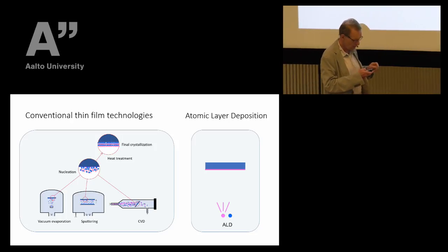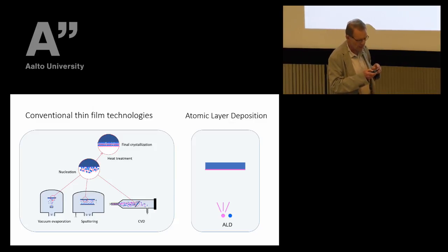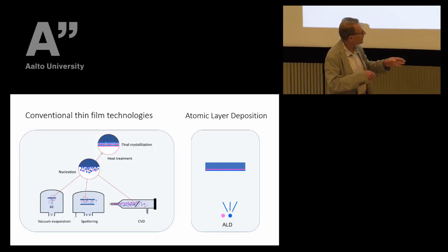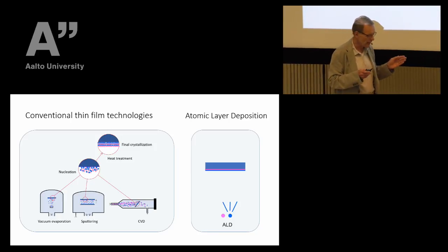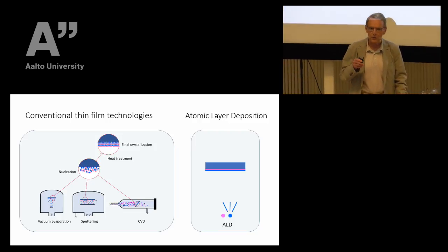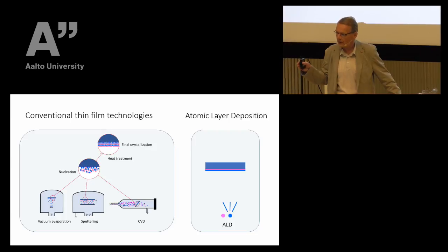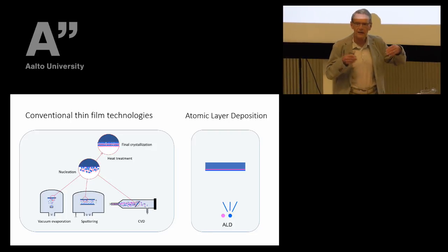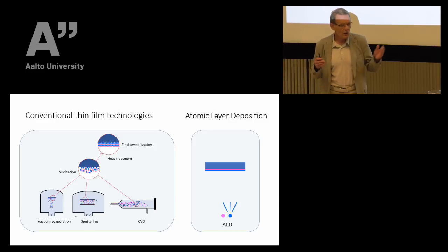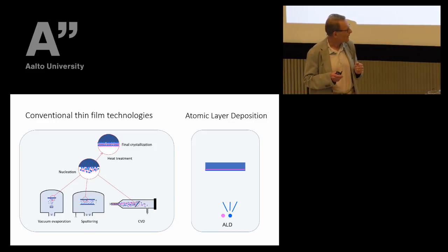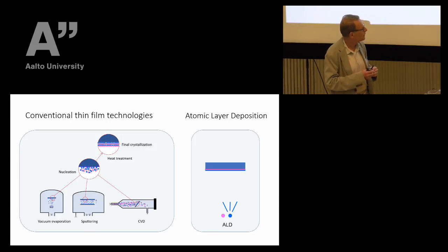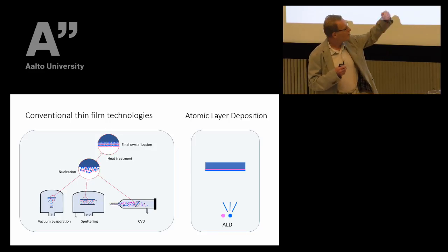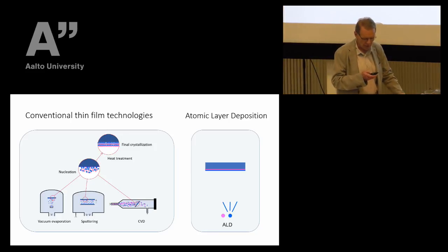So we can dose the material as much as we like, but the surface accepts only one atomic layer. So that's the key in the control. So in the next step, we introduce the second element. It can be used, in some special cases, as the one we started with, zinc sulfide, we can use elements themselves as the reactant. But in most cases, we need some volatile compounds of the source materials, elements of the final compound, in order to create conditions where the reactant doesn't condense but offers the necessary bond with the surface.